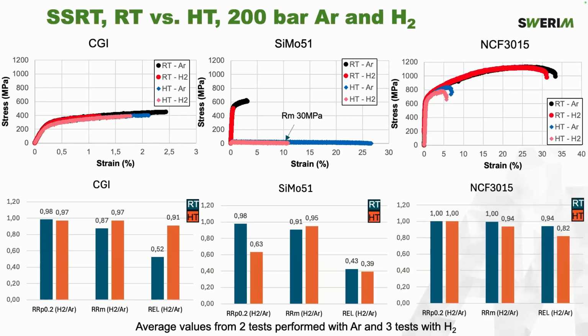For NCF, we don't see any effect on the yield strength. We do see a slight effect on high temperature testing for the tensile strength, and we also see a higher effect for the relative elongation.